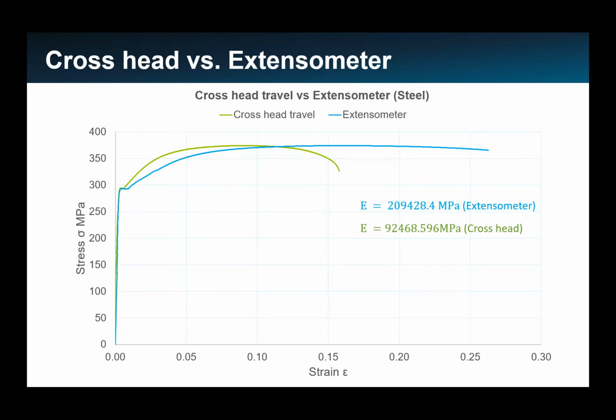The green curve was obtained with the crosshead of the testing machine, and the blue curve was obtained by using an extensometer. So as you can notice, the curves are different, and if we measure the material properties, we can obtain very different results.